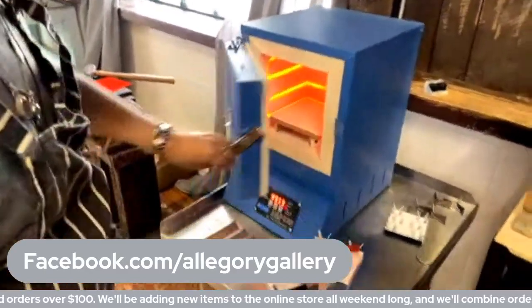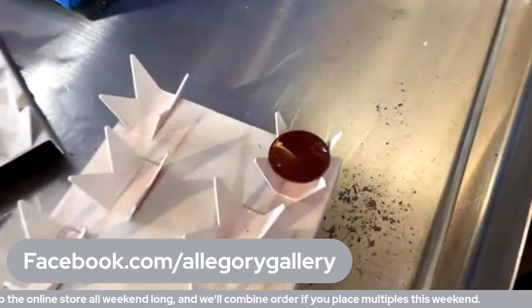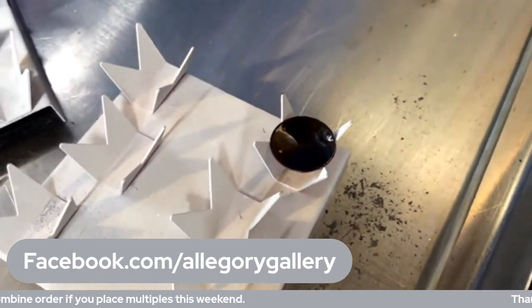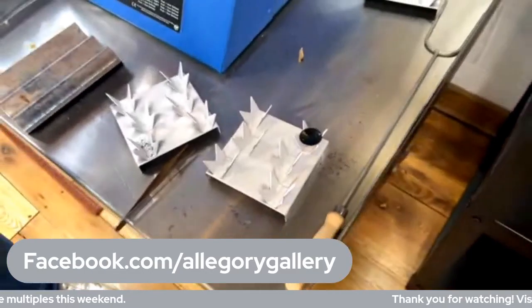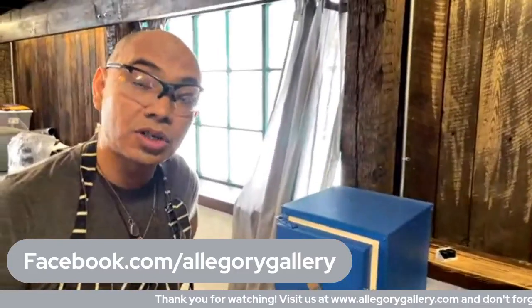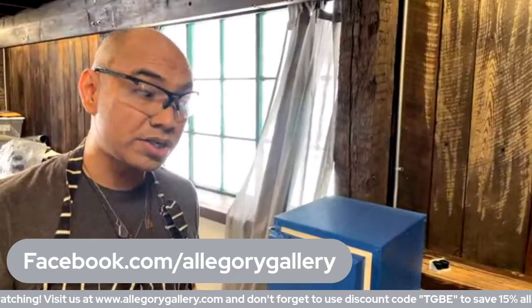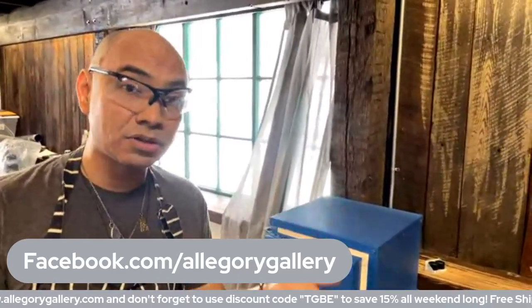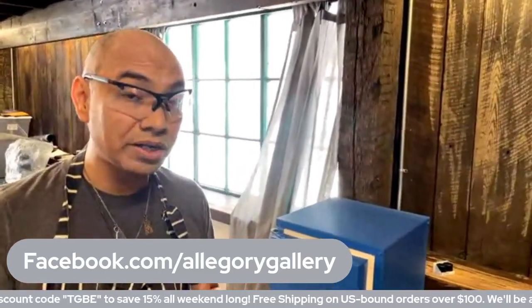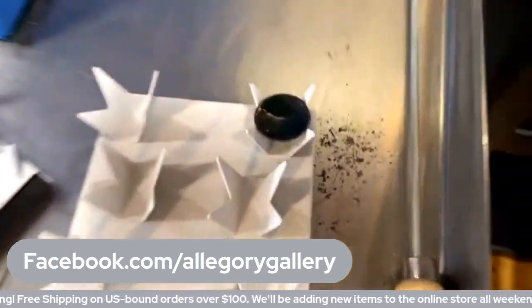So this has been in for about 1.5 to 2 minutes. It's going to look black right now, but that is basically the transparent enamel cooling on top of the copper. The copper is going to look darker. Now, there is a trick when working with transparent enamels. You kind of have to put it in and heat it up several different times. When you heat it up to certain different temperatures, and you have to play around depending on the color, what's going to happen is called clearing the enamel.